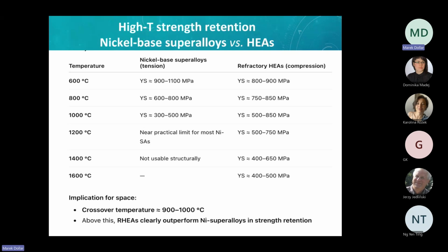So implications for space, kind of this crossover temperature when we are concerned about nickel-based superalloys is around 1000 degrees C, and then the benefits are pretty obvious for still potential benefits. So refractory high entropy alloys outperform nickel-based superalloys as far as strength retention is concerned.